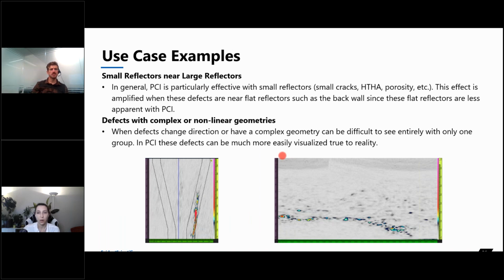And this one here shows again the small reflectors near large reflectors. Because it's not amplitude, it's not as loud, the small reflectors can show much better. And so this effect is amplified when these defects are near flat reflectors, such as the back wall, since these flat reflectors are less apparent with PCI. And also defects with complex or non-linear geometry. So when the defects change direction or have a very complex geometry, it can be difficult to see the entirety of what's going on with one group. And so PCI helps there as well.